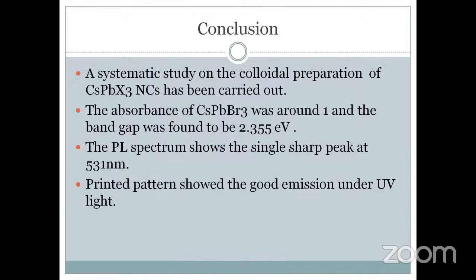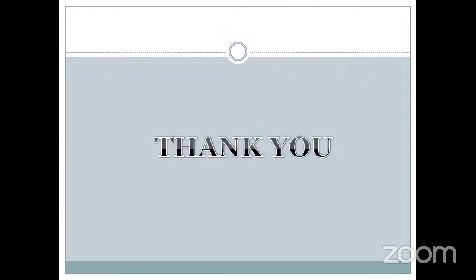So, conclusion: a systematic study on the colloidal preparation of CsPbX3 nanocrystals has been carried out. The absorbance of CsPbBr3 was around 1, and the band gap was found to be 2.355 electron volt. The PL spectrum shows a single sharp peak at 531 nanometers. The printed pattern showed good emission under UV light.